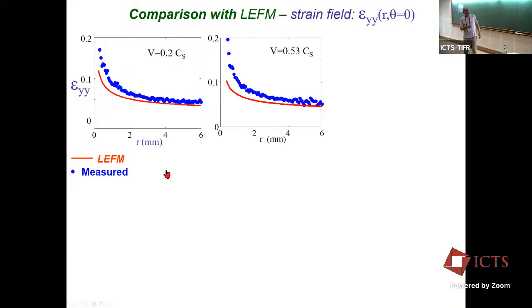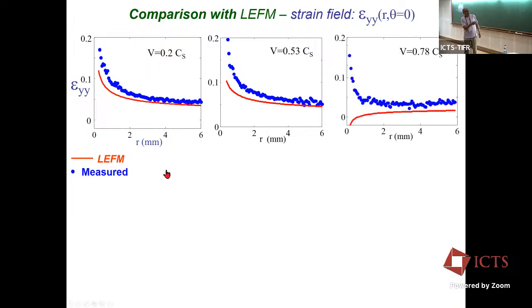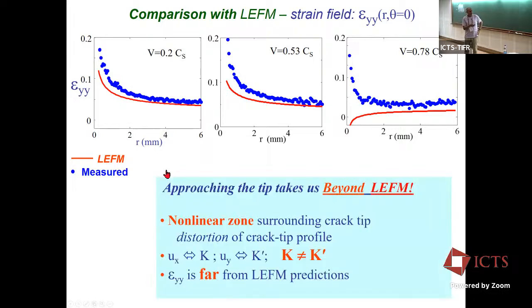By the way, if we look at these experiments and compare them as a function of velocity to the predictions, this is the linear elastic fracture mechanics prediction of the strain field. We find that the faster we go, the worse the theory gets. In fact, this one tells us that cracks should be under pressure, not under tension, as you approach the tip. And these are what we actually measure. So Eran said,